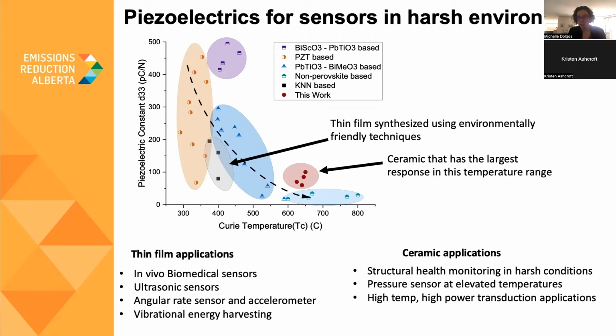We've also synthesized a novel ceramic piezoelectric material that we're in the process of applying for a provisional patent for. And this material has a higher operating temperature of about 600 degrees C. And you can see on the plot that our ceramic has a larger response, so it's more sensitive than other materials that have that similar maximum operating temperature.